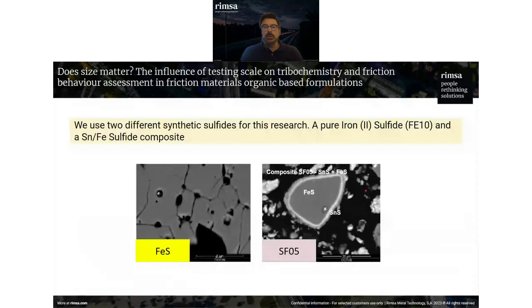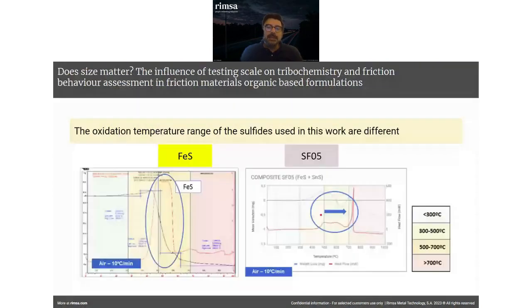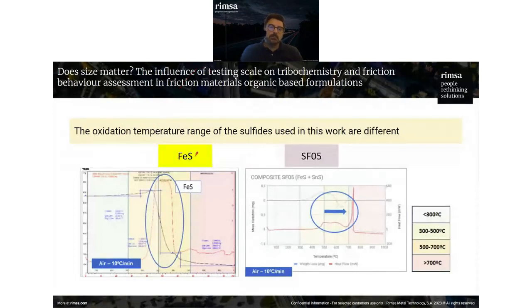In this case, we are going to use the sulfides as a marker to follow this reactivity beneath the surface or in the surface of the brake pad, and we'll compare what happens in a friction material tested in a dynamometer, and the same friction material tested in a tribometer. For this, we are going to use 2 different sulfides as a marker. One will be the iron sulfide, and one will be a composite sulfide that is a core of iron sulfide coated with tin sulfide. This gives a different oxidation profile for each one of these 2 sulfides.